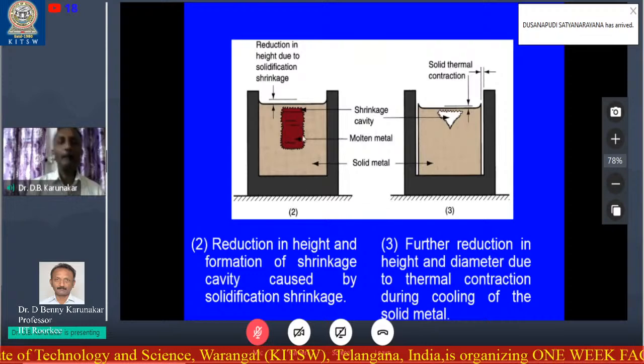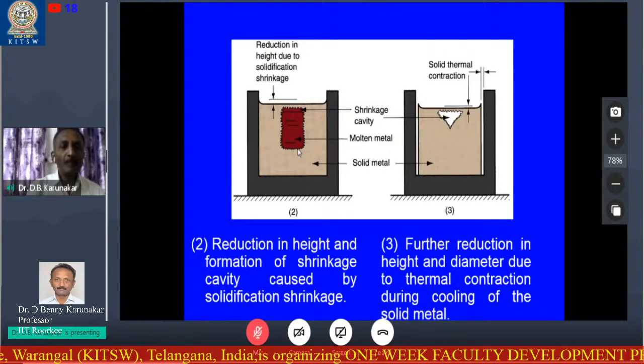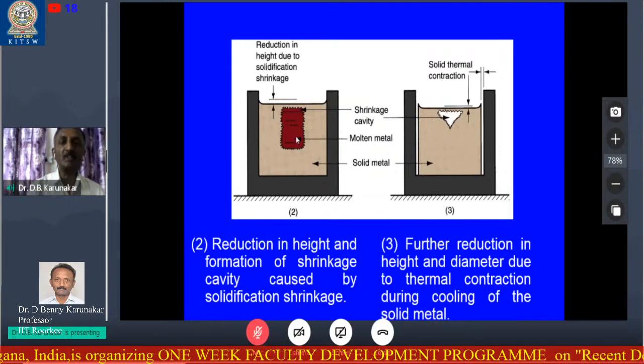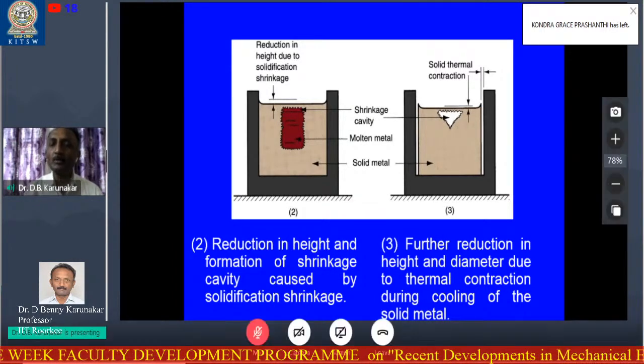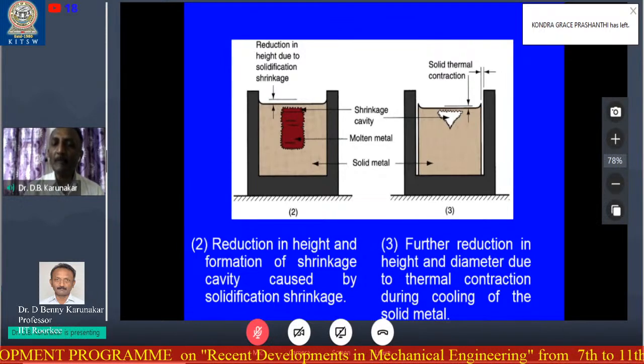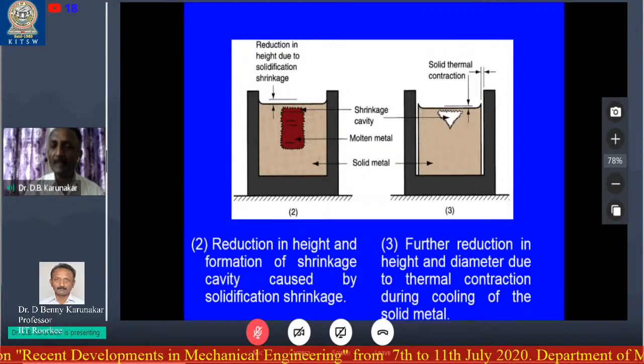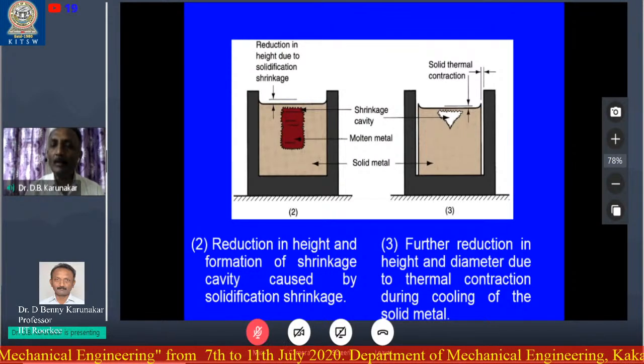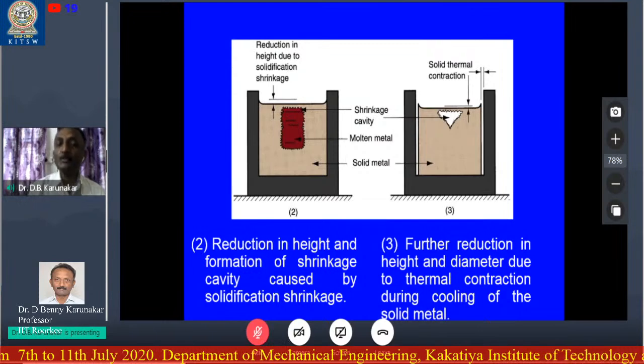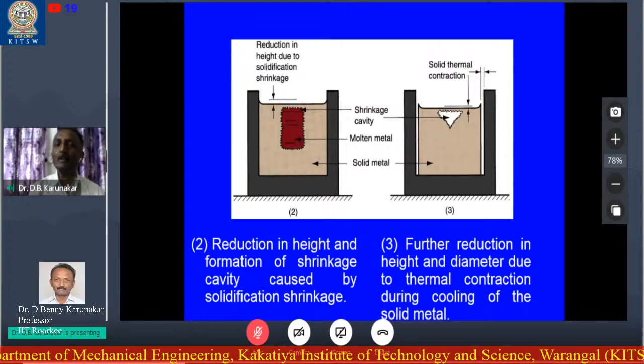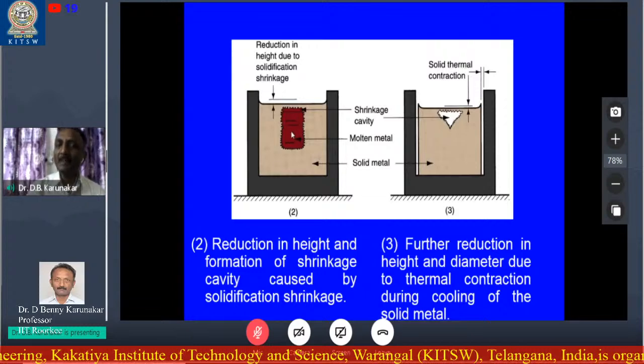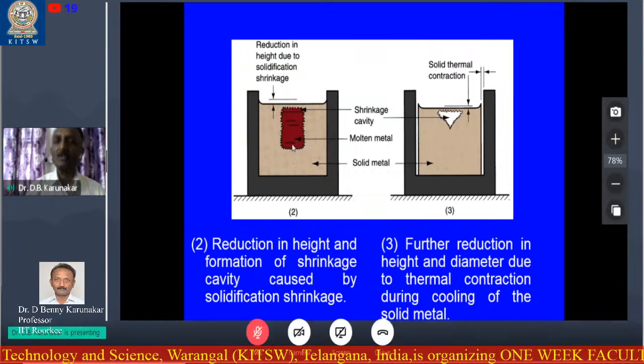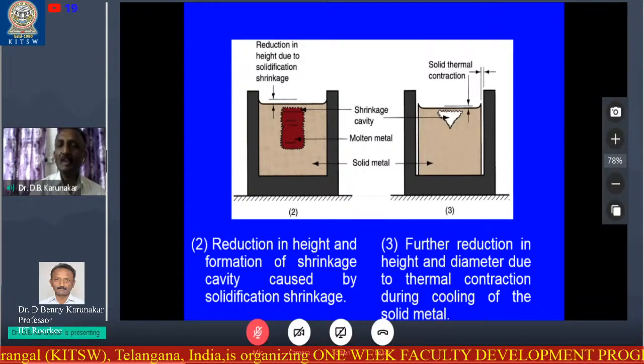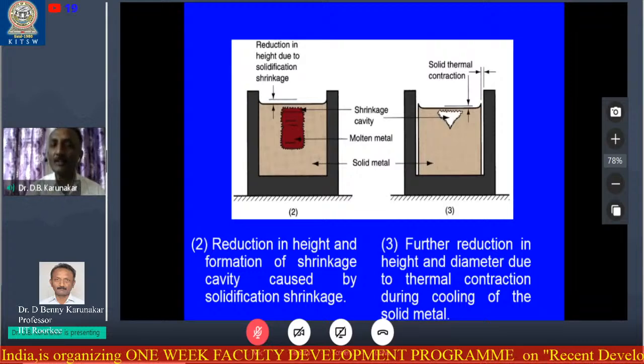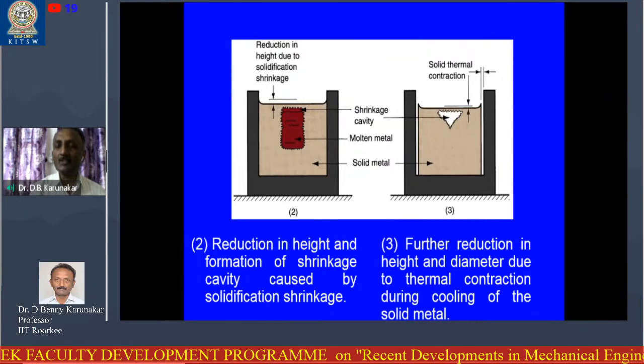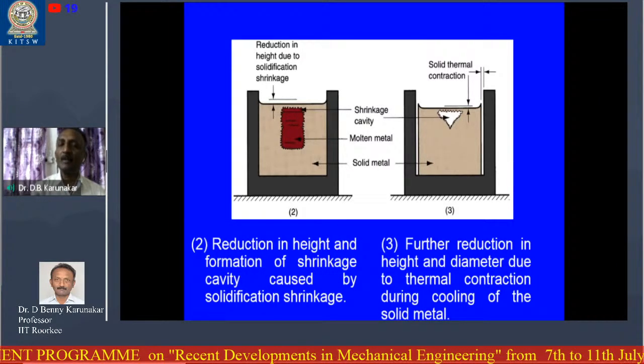Next one, you see, again, this is the reduction in height due to the solidification shrinkage. Now it has come down to the melting temperature. Once it comes to the melting temperature, there is no further change in the volume due to the temperature drop. In fact, during the transition of the phase, the temperature remains constant. But there is a shrinkage. This is known as the solidification shrinkage. So far, we have seen one is the liquid shrinkage, the other one is the solidification shrinkage. During this shrinkage, the temperature remains constant till the solidification is completed.